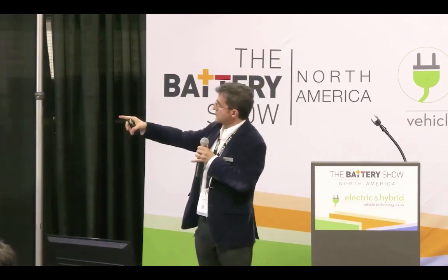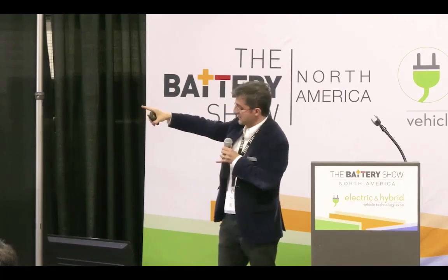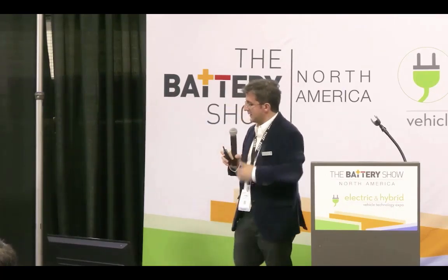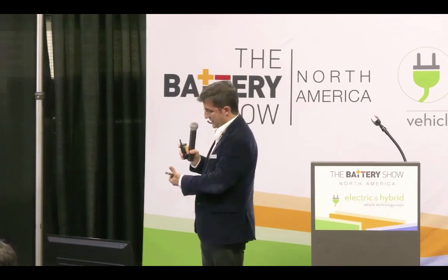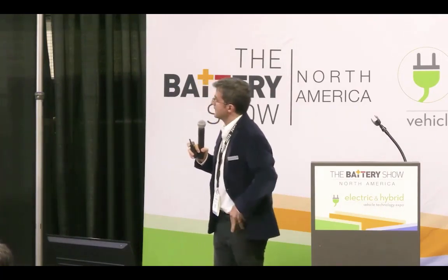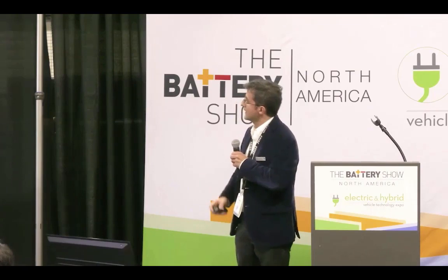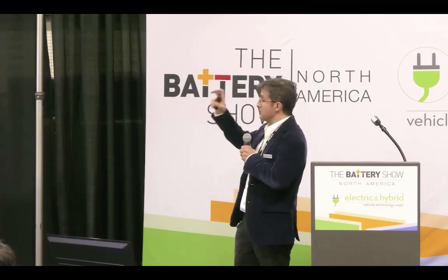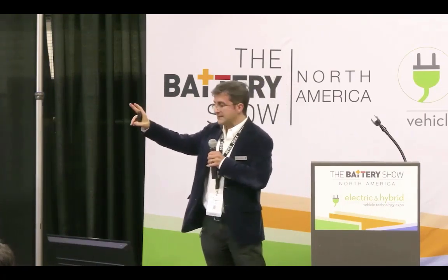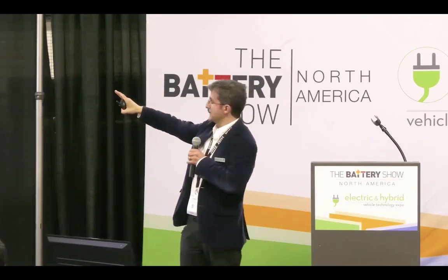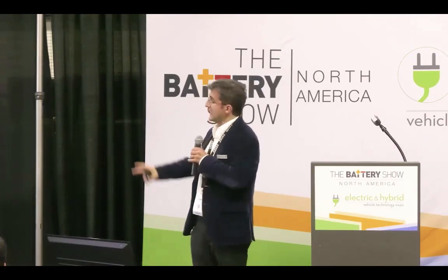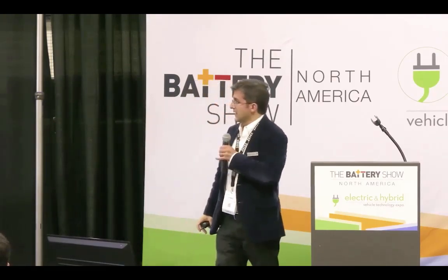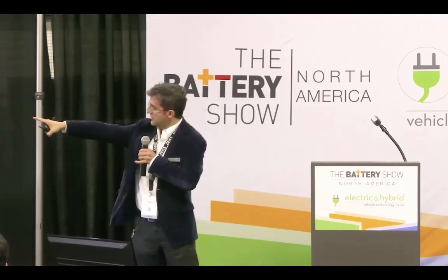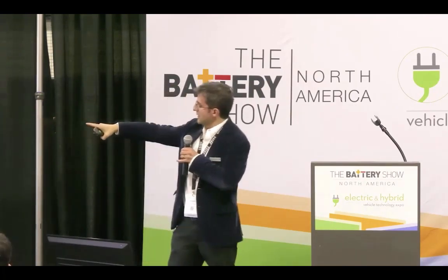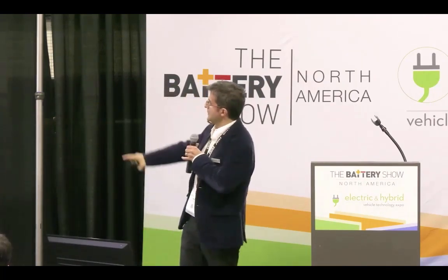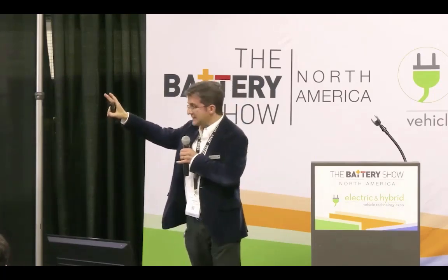This is also another pouch battery, and you see a section of the battery being slid through in this portion of the battery. In here, what you see is the comparison of two different scans. One is a fresh battery, and another is a battery that has been cycled 200 times. And you can see that in the first one, you can see those bright spots, which are part of the silicon anode, and in the 200 cycles, it has disappeared.